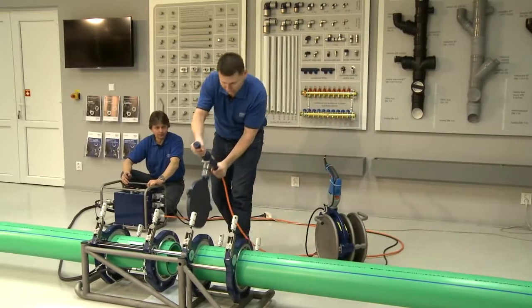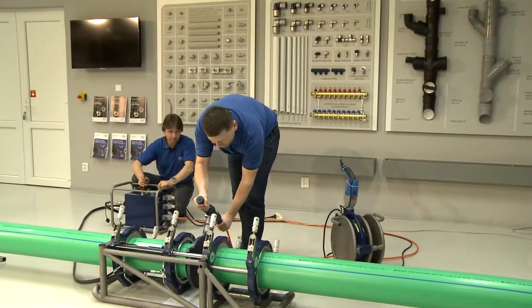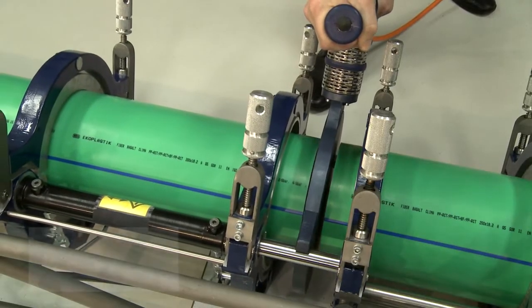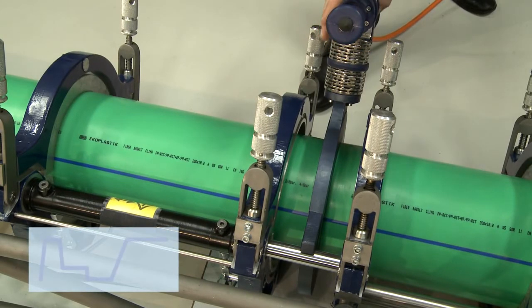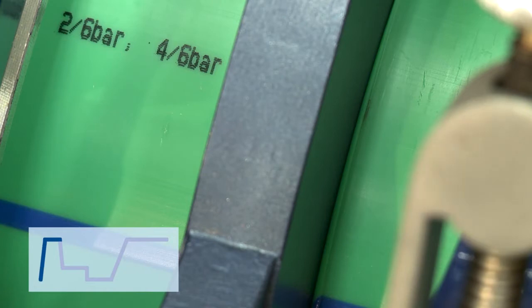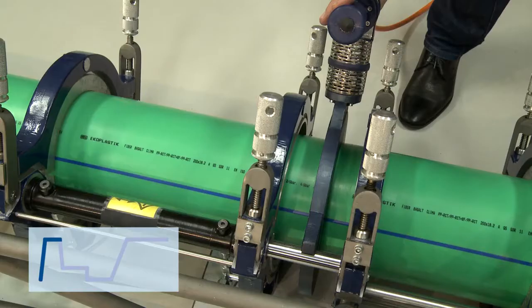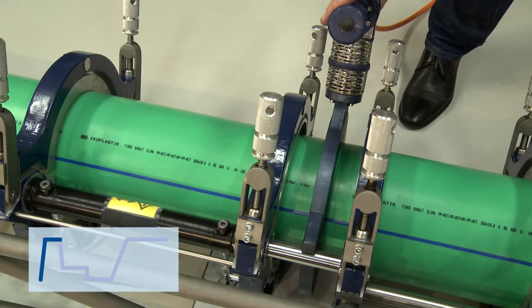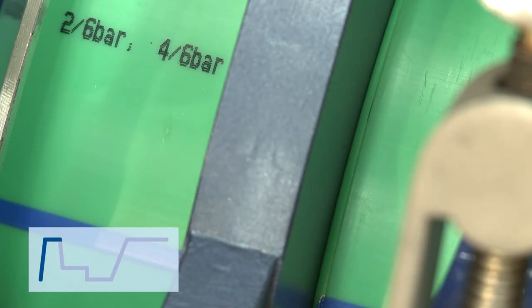Now insert the heater between the pipes and press both pipe ends against the heater using the preset pressure. This is called the balancing welding pressure. The pressure and temperature gradually melts both front ends of the pipes. A weld flash should form around the entire pipe's circumference as indicated in the chart. This evens out the welded surfaces.